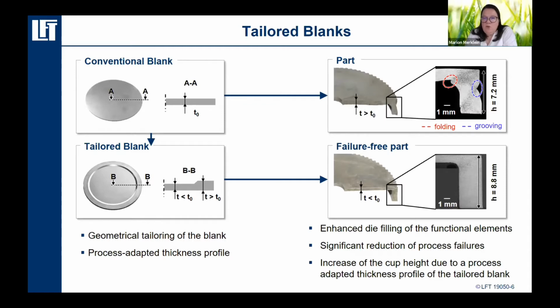We can improve the quality, because in such a case, that is a component similar to a synchronizer ring, we need some geared teeth at the outside. And so especially the geometry and the accuracy of these gear teeth is very, very important in order to guarantee the function of the component afterwards. And so what we saw is that we can improve the height of such gear elements by about 20 to 30%. That can be correlated directly with the increase of sheet thickness we can realize with a tailor rolled blank. And we can avoid the material backflow that is responsible for the folding of the material.